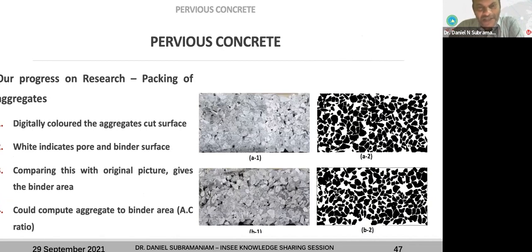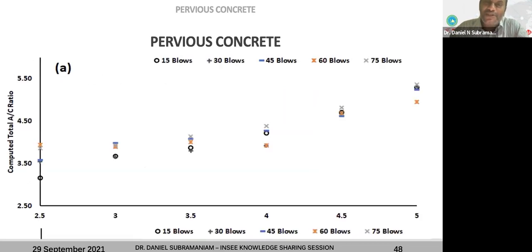So then after that, we did another further analysis on image. This time we actually marked the aggregates alone, and we left the binder also out. So binder is also now considered into the white area. So we can do the same analysis comparing with the previous analysis, so you get the binder thickness as well. So binder, aggregate, pores are now 3 separated. And when we did that, we found out that for higher AC ratios of 2.5 or 3 or whatever, when we did the compaction, it became around 4. So you can see that with compaction, it actually comes to somewhere around 4.